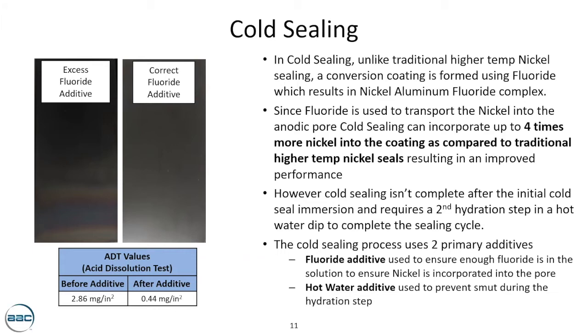So if you are getting iridescence, that's usually a result of over sealing, which could mean you have too much fluoride, or you're immersing the part in that bath longer than it needs to be immersed. Now, if you look at the ADT values, the values prior to adding the additive and once the additive is added, you'll see significantly lower numbers than what you've seen in the previous two slides. Before the additive, you're already at 2.86 milligrams per square inch, but after you make the fluoride addition, you'll see your ADT value drops precipitously.